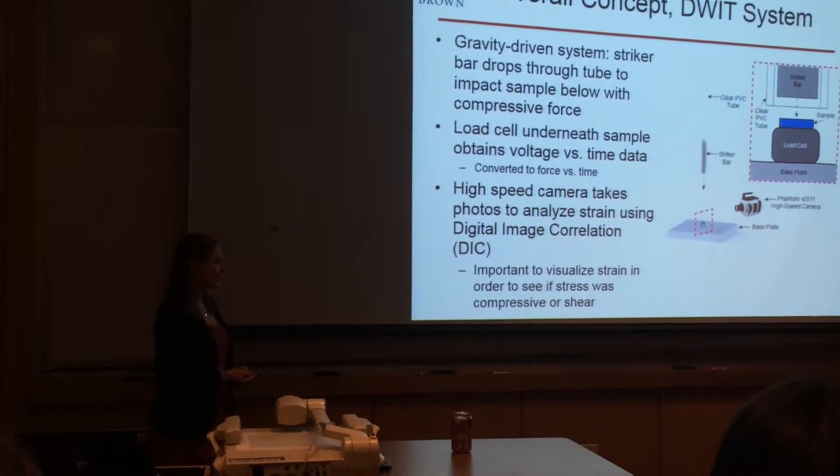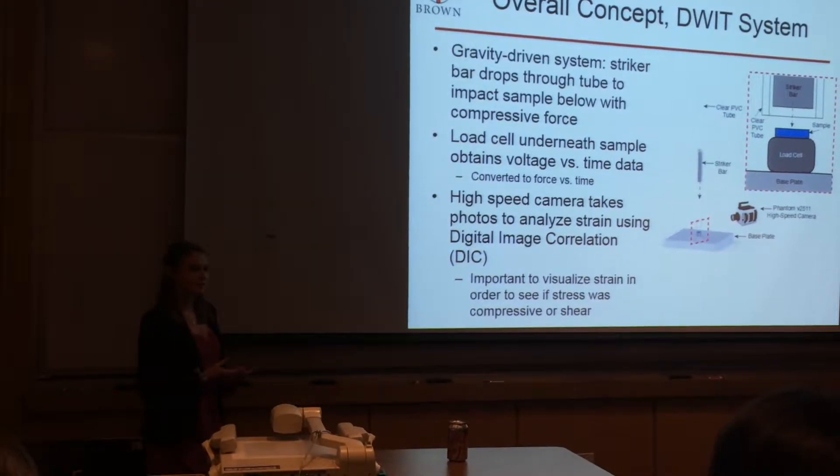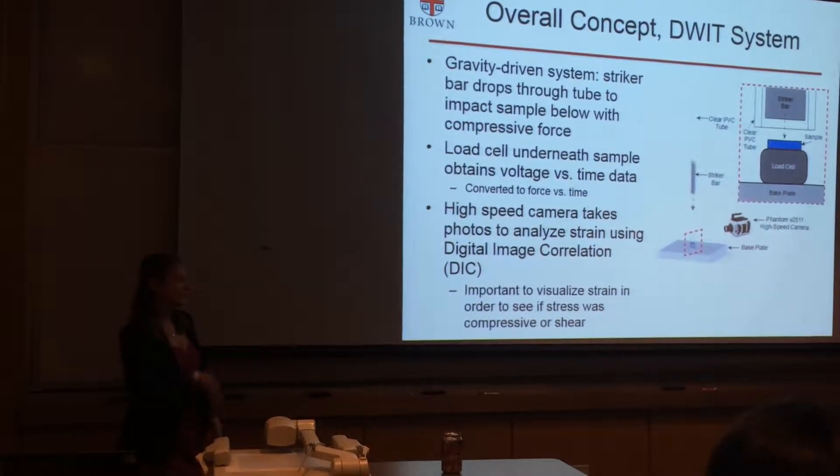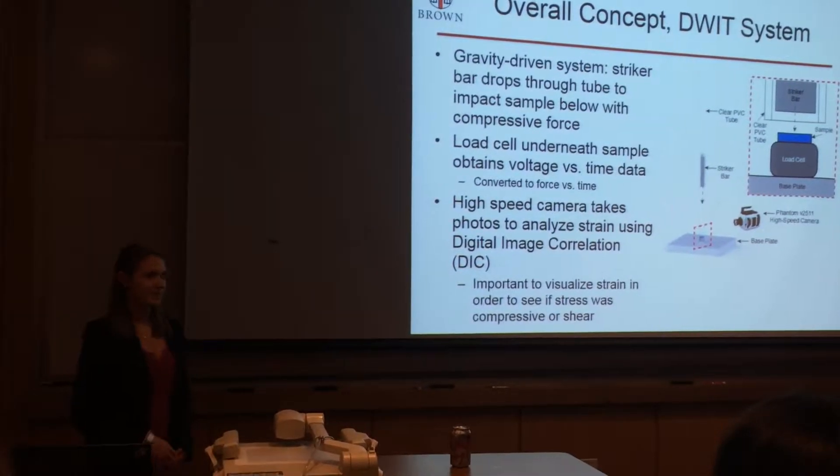It's really important that researchers can actually see what's happening to the sample during the impact so that they know that it was a compressive stress as intended rather than a shear stress which can happen if something is misoriented in which case the researcher should obtain new data.